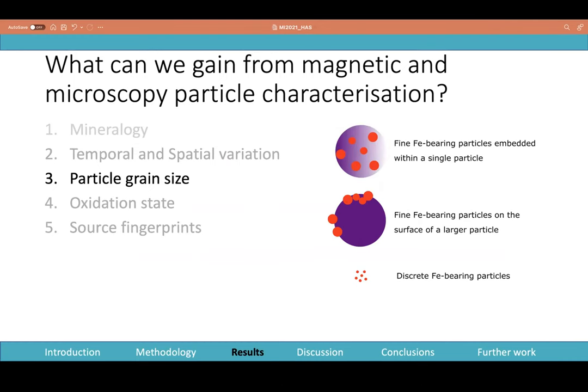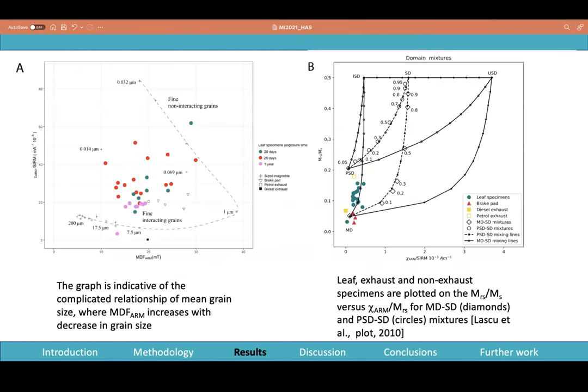So the idea was to characterize them using different methods and to compare what different magnetic granulometric graphs can tell us about the relationship of these particles. This graph over here is basically ARM susceptibility normalized to the SIRM plotted against the MDF, which is the median destructive field. It basically tells us, when you demagnetize the samples in an AF demagnetizer, how much of the remanence it loses. This is plotted over there. This is the susceptibility plotted.